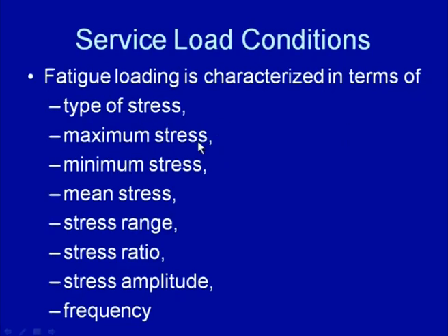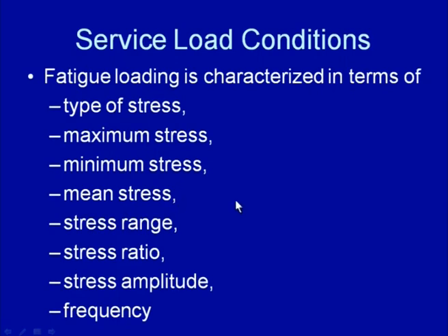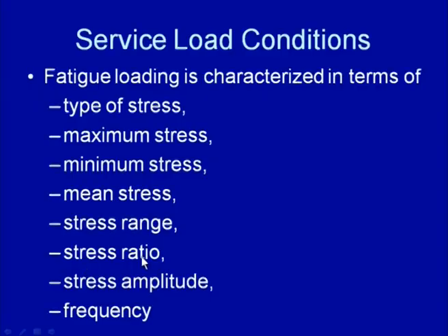Similarly, an increase in maximum stresses and a decrease in minimum stresses, which increases the stress range, will adversely affect the fatigue life. An increase in the value of the mean stress of the tensile kind will facilitate crack growth and thus reduce the fatigue life. An increase in stress range will reduce the fatigue life, and decreasing the stress ratio will also reduce the fatigue life. The greater the stress amplitude, the lower will be the fatigue life of the component.